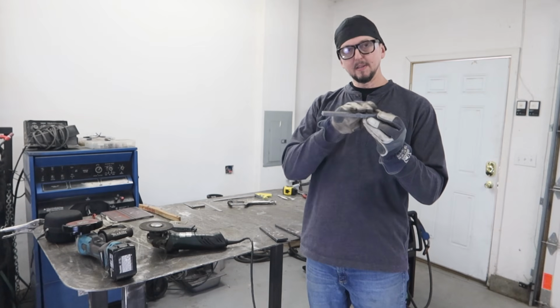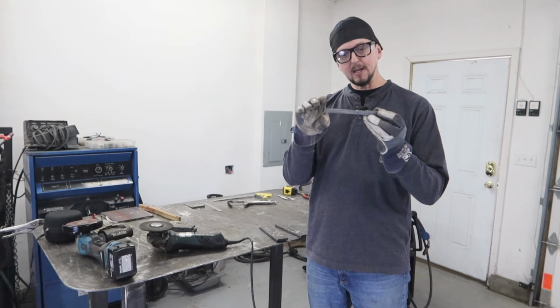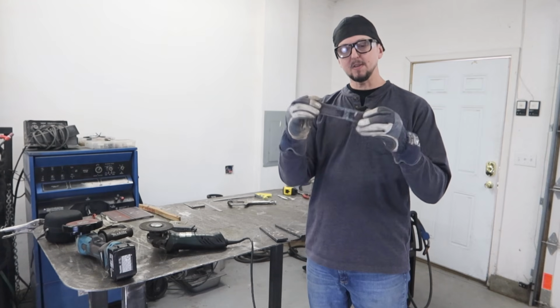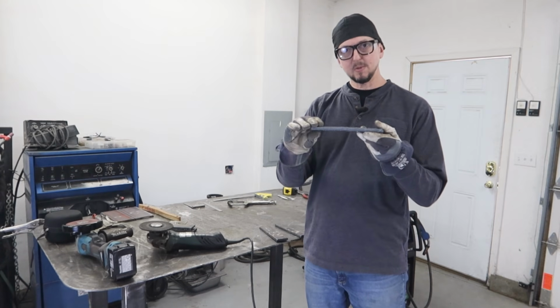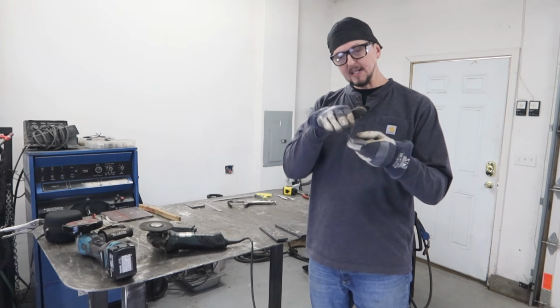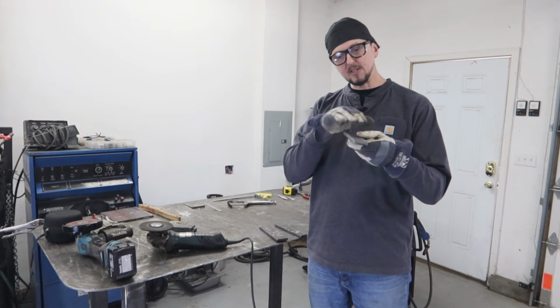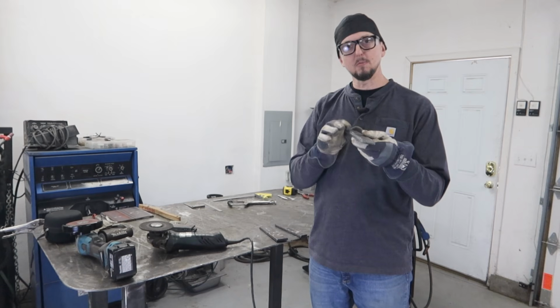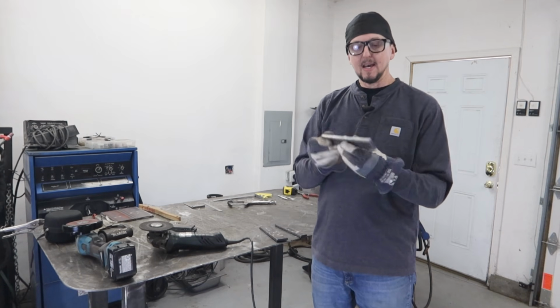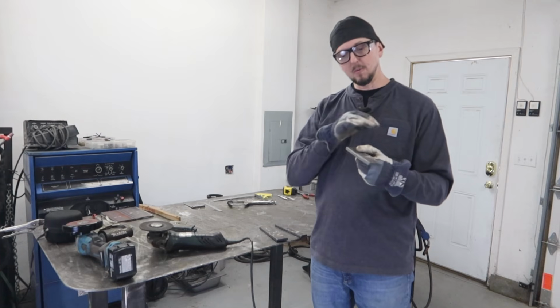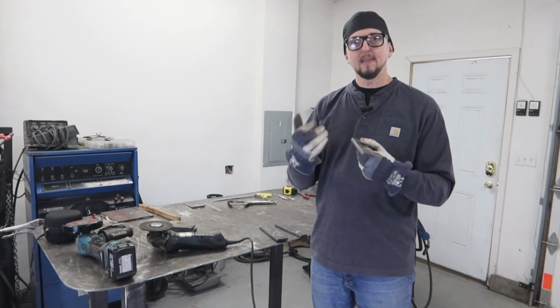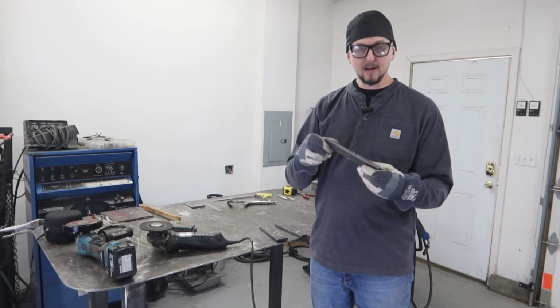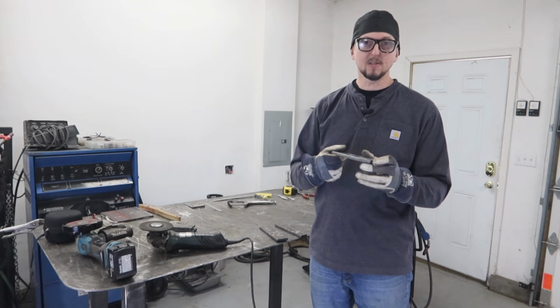Once we get the face weld flush with the surface, and the root side flush with the surface, then we're going to clean up these edges, and we're going to break these edges so that we have a nice radius, no more than a 1/8 inch radius. And that will also help our bend test. We don't want any sharp angles anywhere that can be areas where cracking can start to propagate.